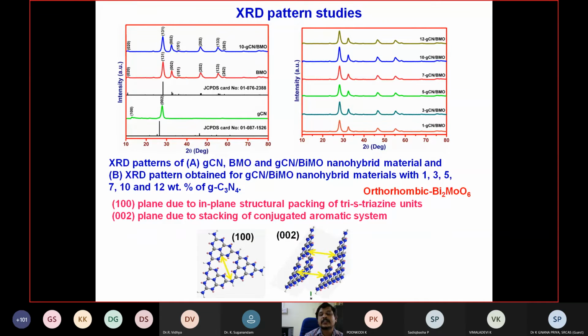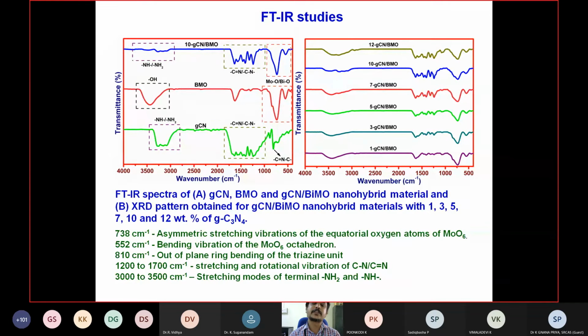Then we have done the XRD analysis. The XRD analysis clearly reveals the orthorhombic structure of bismuth molybdate and also the presence of graphitic carbon nitride in that nanomaterial. The addition of graphitic carbon nitride into the bismuth molybdate does not affect the crystalline property, and there is no significant change in the crystal plane positions. Also, we have varied the graphitic carbon nitride content in the bismuth molybdate, and there is no appreciable shift in the XRD pattern. So we clearly confirm that this addition of graphitic carbon nitride does not affect the crystalline property of this bismuth molybdate. Then the FTIR spectrum we have also recorded.